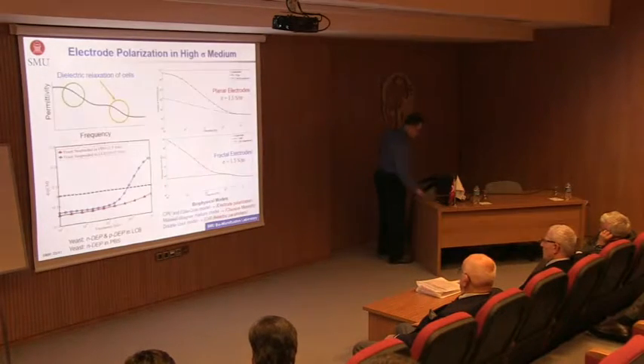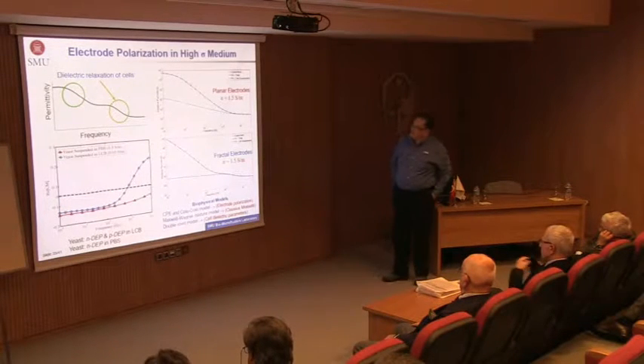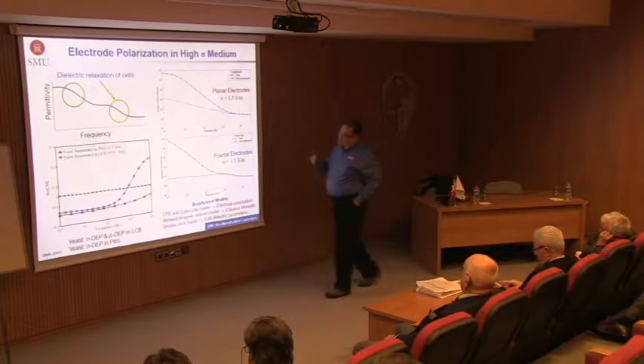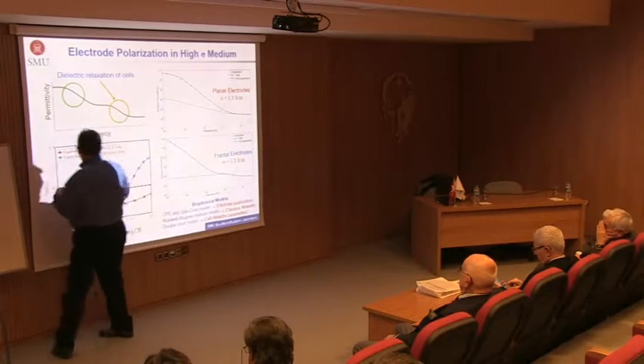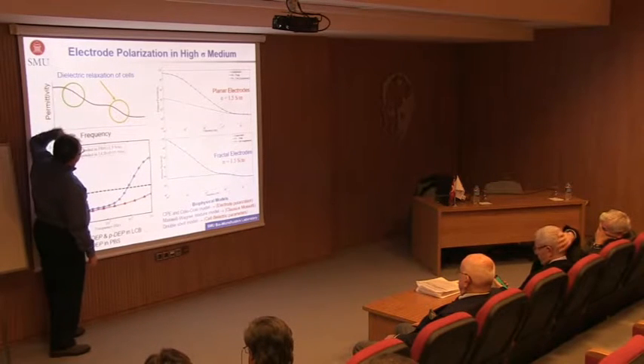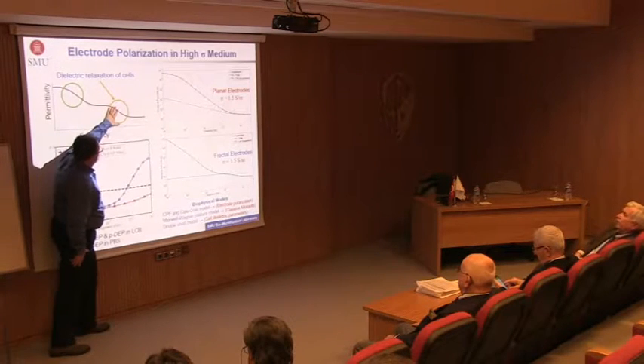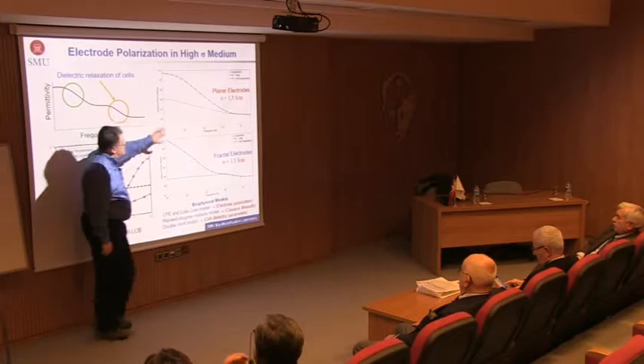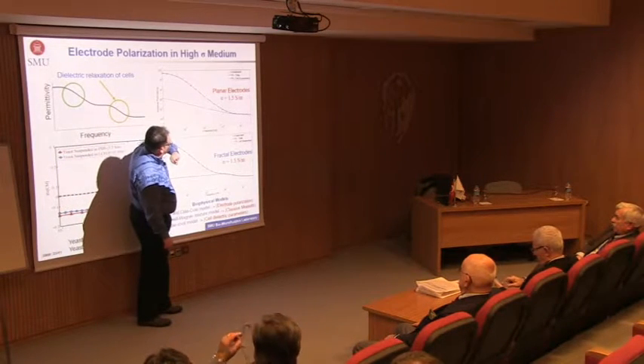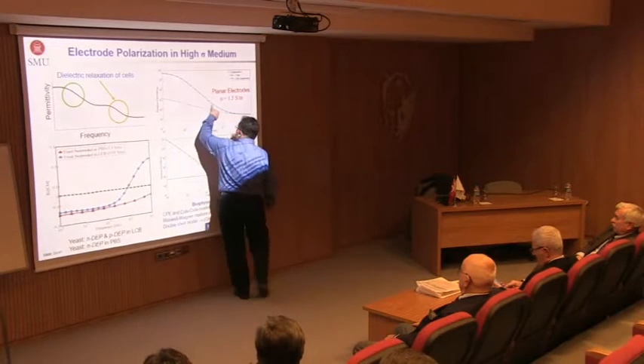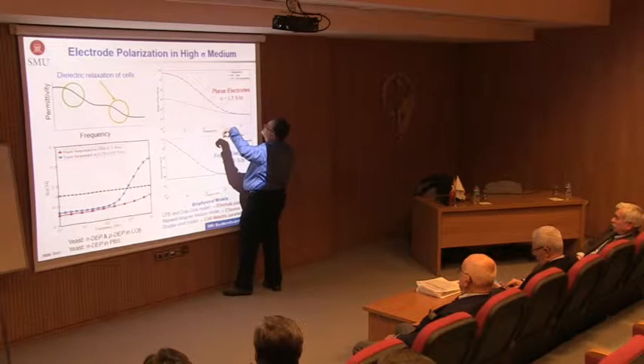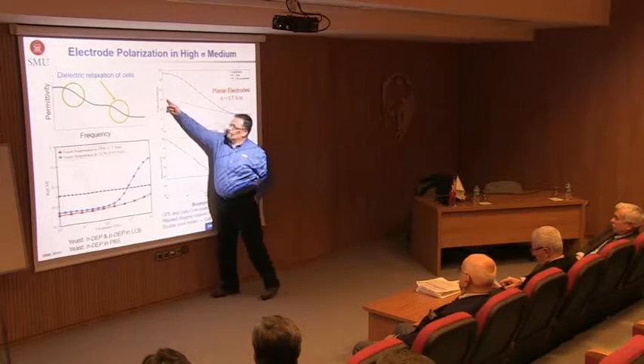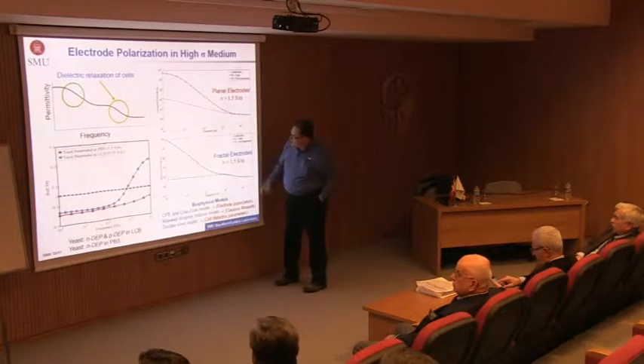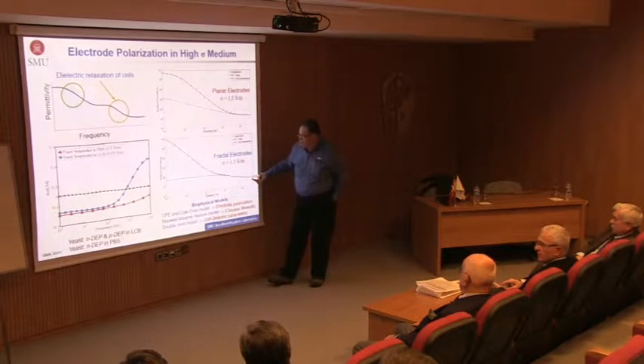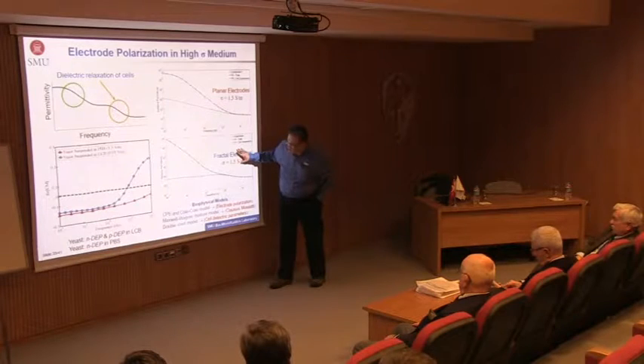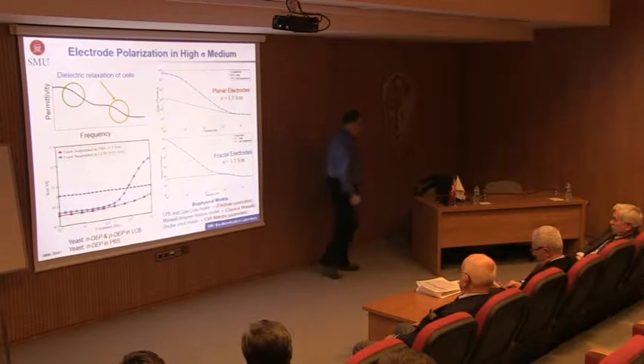So that actually pushed us towards something different, almost like material science a little bit. But first, what we realize is that you expect that there are electrodes, and there's going to be dielectric effects coming from the electrodes, and there will be an effect due to dielectric relaxation of cells. When you do this in basic electrodes that we fabricated in 1.5 Siemens per meter, that's the data. This is our fit, and when we work out basically what happens to a cell suspension, we get something like this. We cannot use this. What we need is something that we can apply the Cole model to, and indeed we could do this if we can actually change our electrodes from plain electrodes to what we call fractal electrodes.